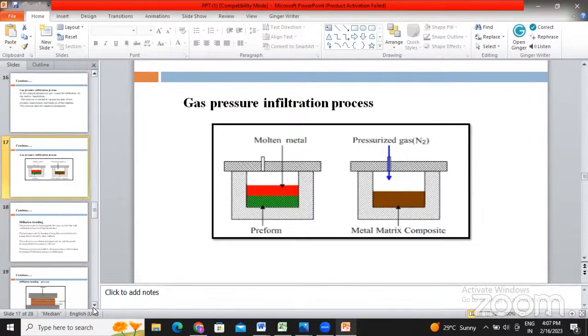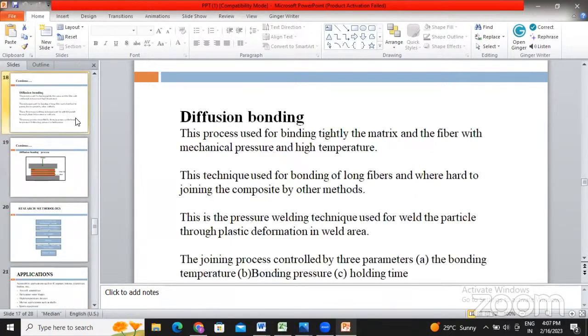gas pressure infiltration process. And next is diffusion bonding. This process is used for binding the matrix and the fiber tightly with mechanical pressure and high temperature. This technique is used for bonding of long fibers and where hard joining of composites is needed by other methods. If you require a high quality of joining, that joining depends on the bonding temperature, bonding pressure, and holding time. That is basically a pressure type development of the composites.